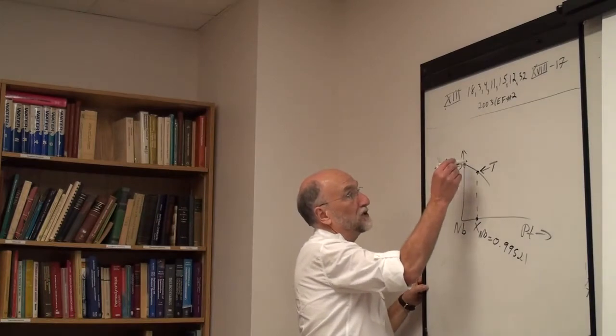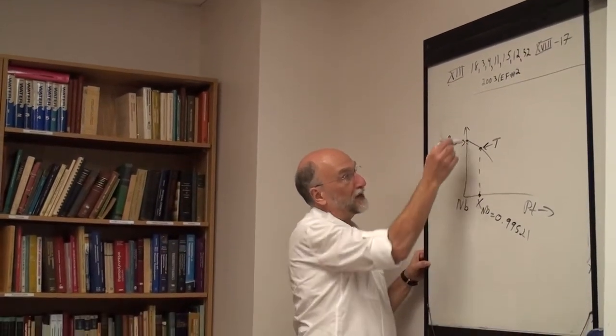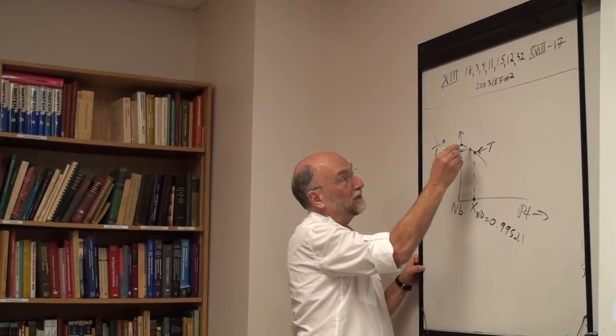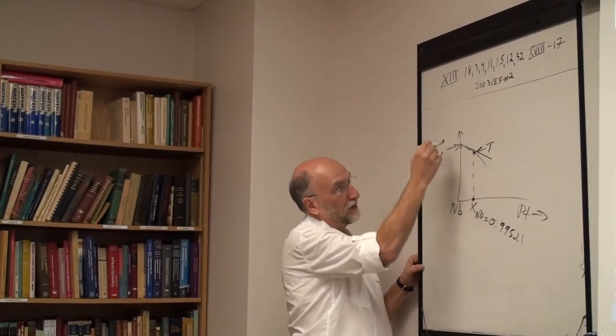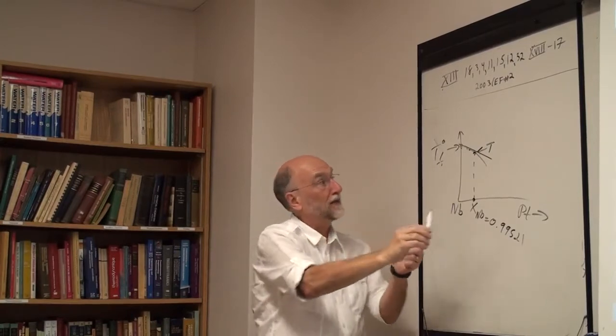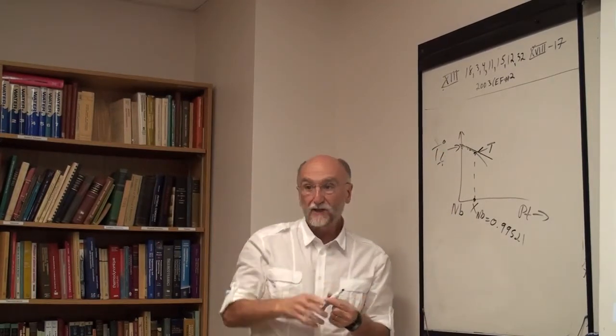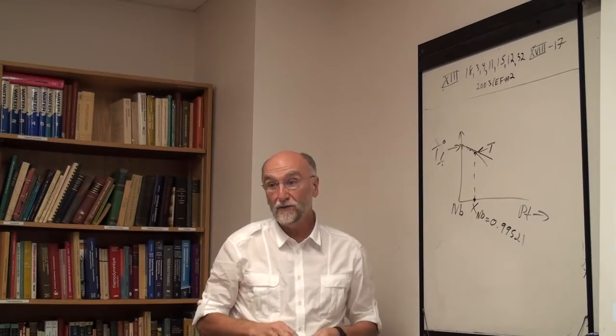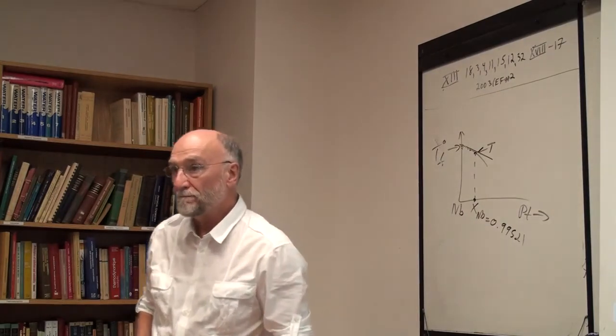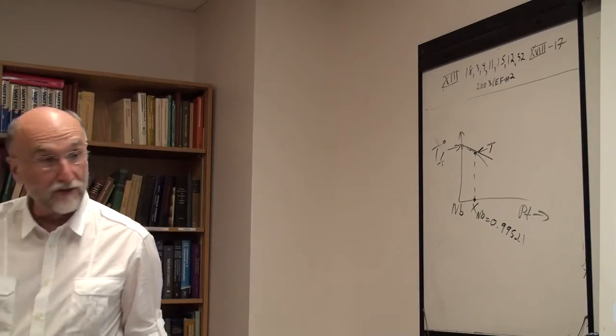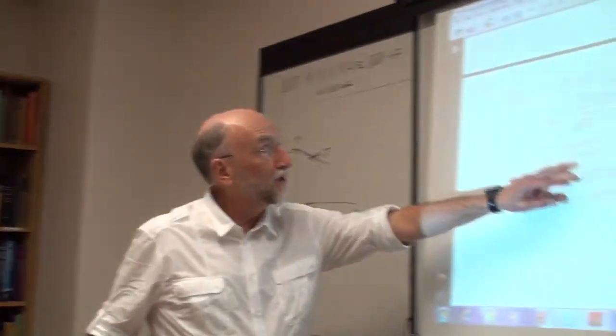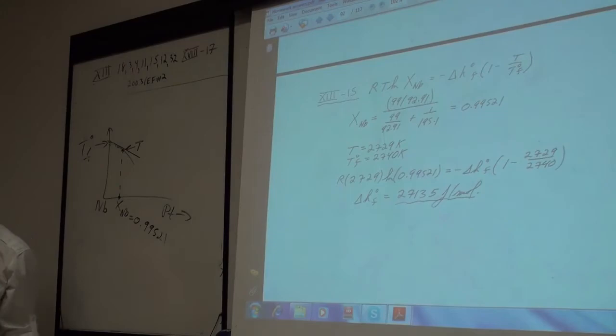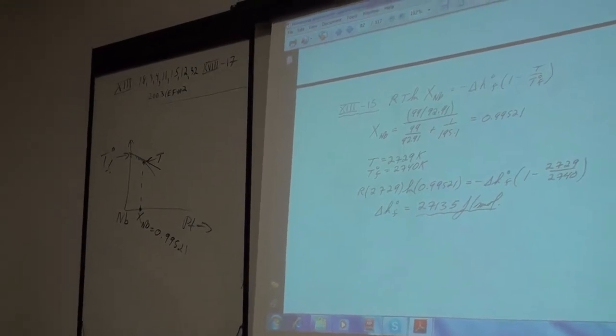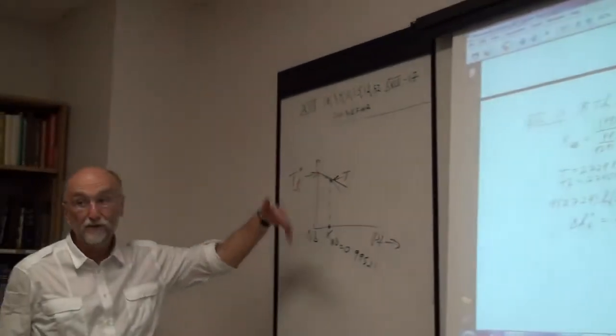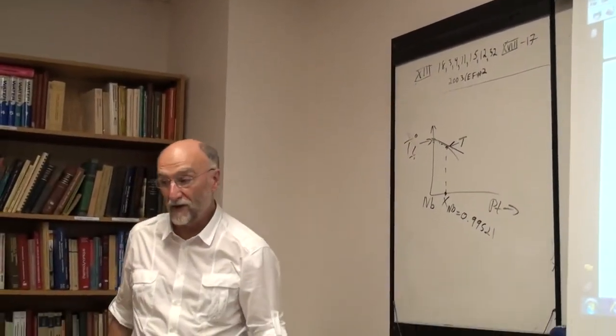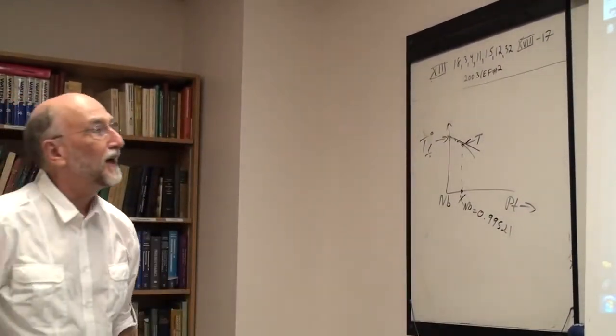So what you really should do is, of course, even at 1 weight percent, it might deviate a bit. So what you really want to do is measure a few points and then with your ruler make a limiting slope, taking the slope as the mole fraction approaches 1, and then all the approximations drop out. Okay. And this is a more accurate way of measuring the heat of fusion of something with such a high melting point than calorimetrically. Calorimetrically, you're never going to measure something like that at that temperature, but measuring the cooling curve is an awful lot easier than measuring calorimetrically.